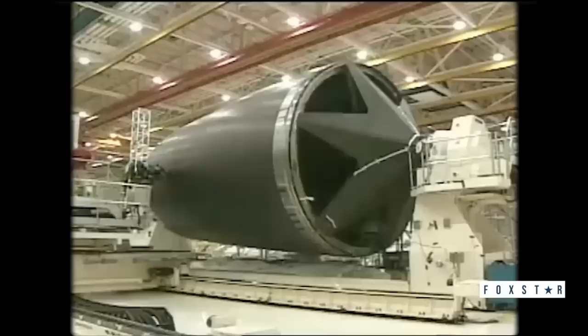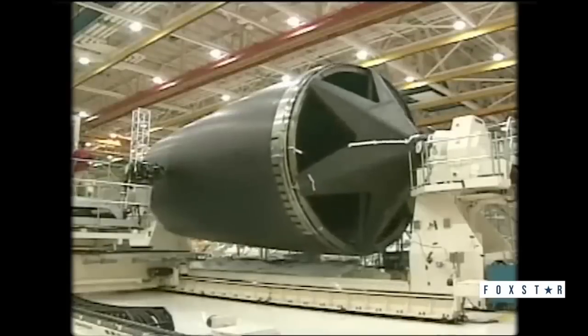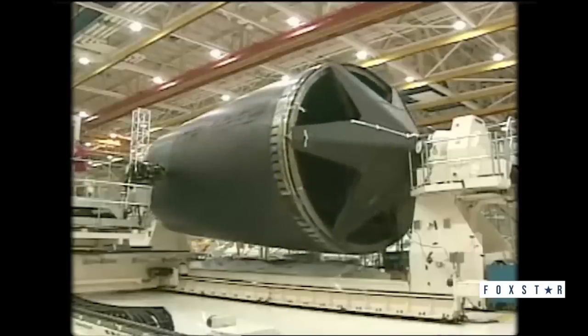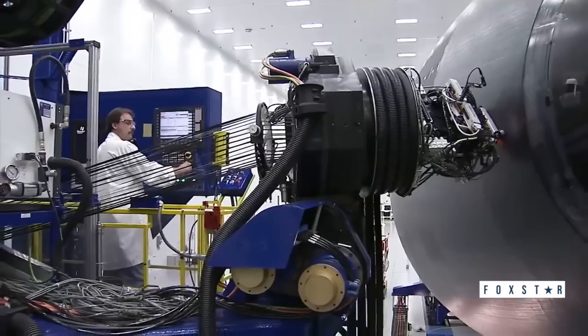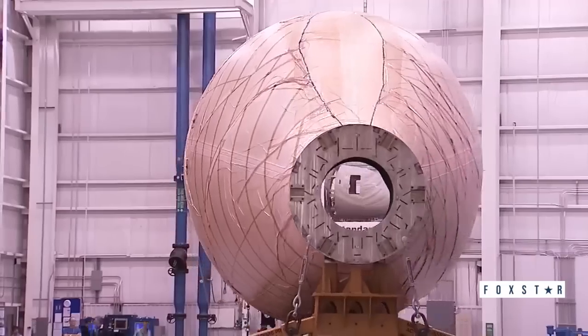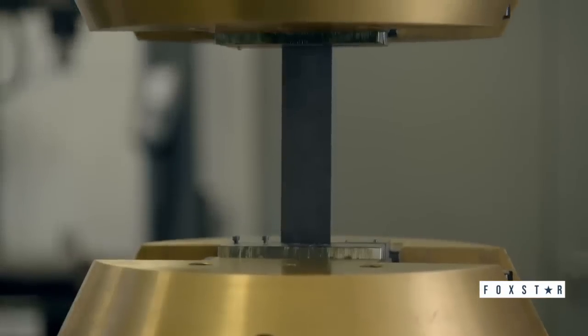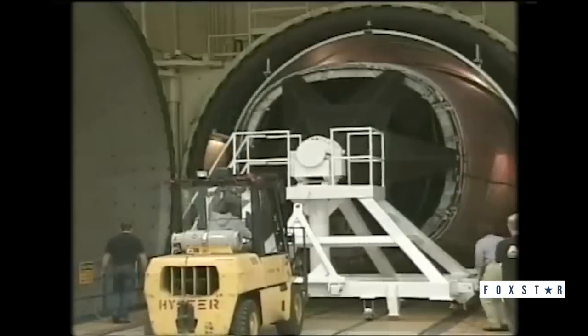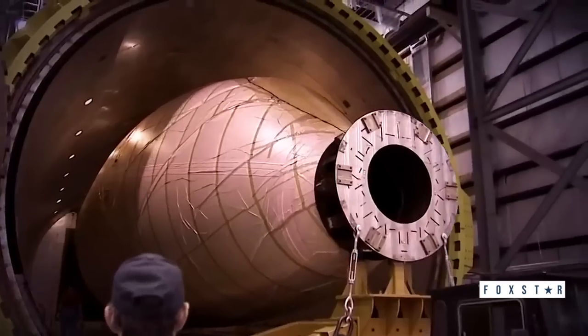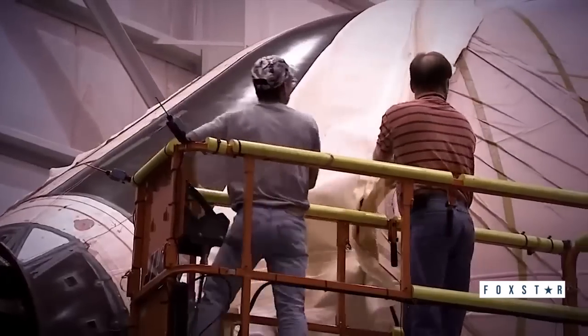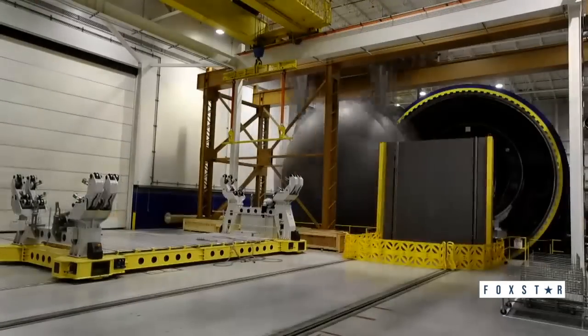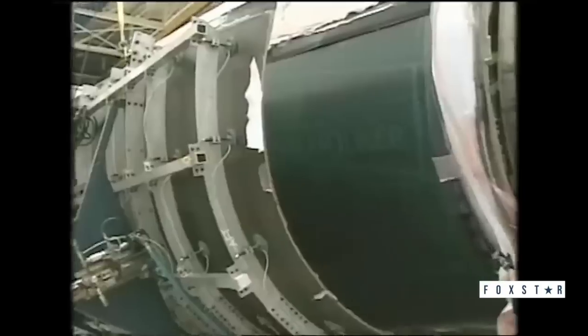The 787's fuselage is created by wrapping a carbon fiber tape impregnated with a plastic resin around a rotating mold of the fuselage. This machine precisely controls the overlaps of the tape and the orientation of the fibers to ensure we are getting the most out of the carbon's tensile strength to resist the internal pressure loads and the longitudinal bending loads the fuselage will experience. One of the problems with this manufacturing method is that the part needs to be placed inside an oven to cure the resin. This hardens the plastic and creates a solid composite structure. Ovens the size of a wide-body jet airliner fuselage are not exactly common, and this is often the limiting factor on parts made this way, and requires massive upfront investment to build a customized oven large enough to fit the part. But the benefits are well worth it.